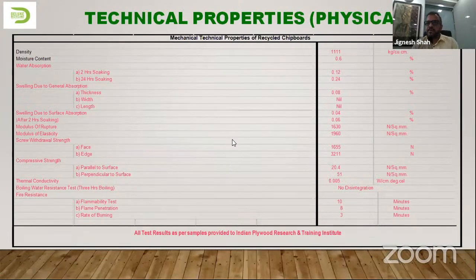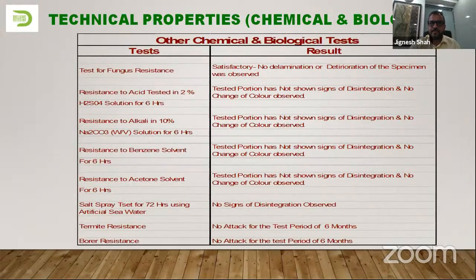These are some of the technical properties. I think the key property that we look at is the water absorption. Within 2 hours and 24 hours of soaking in water, the absorption is less than 0.24%. These are some tests done on the biological and chemical side. So you see the fungus and acid resistance, alkaline resistance, benzene, solvent resistance, salt spray resistance, termite and borer resistance. All our boards are tested for these and they're fine with these kinds of tests.